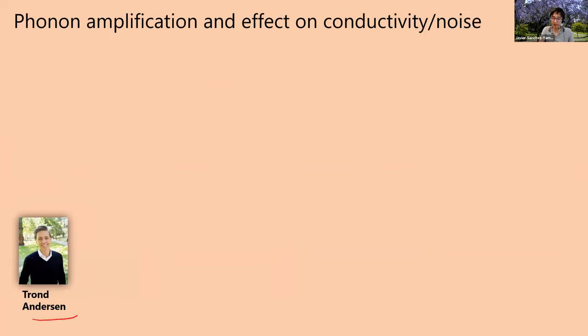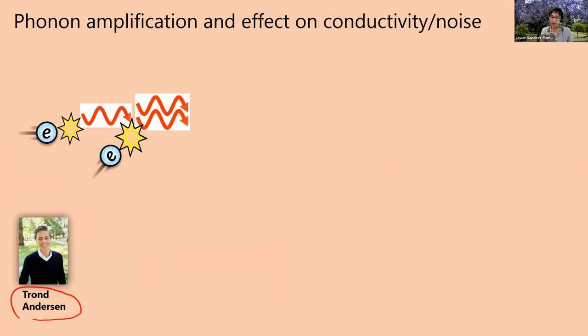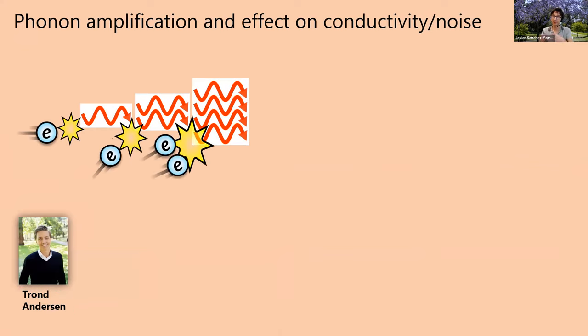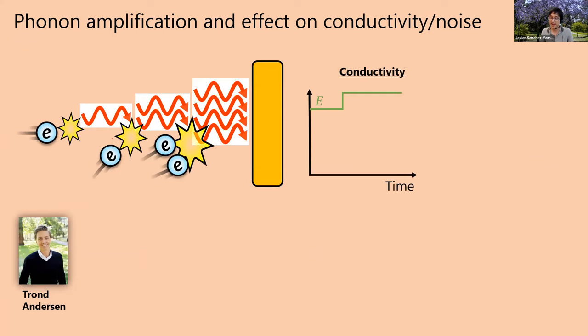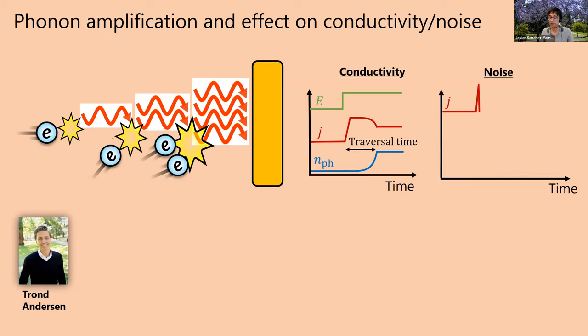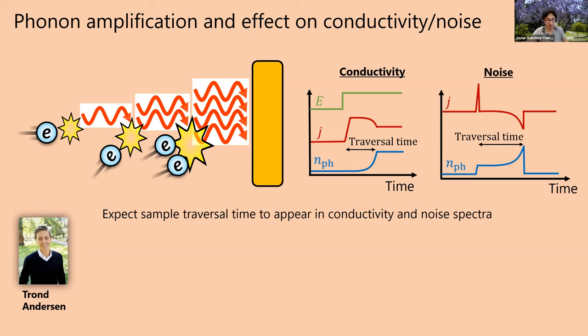So we had this great grad student, Trond Andersen, who developed the theory for all of this model. Exactly this model describes the process I just told you about, where an electron can emit a phonon, that phonon can stimulate the emission of another phonon, and this leads to a cascading process where phonons are exponentially growing across the sample. And it turns out that this can explain both the suppression of the conductivity and also the noise features that we saw at low frequencies.